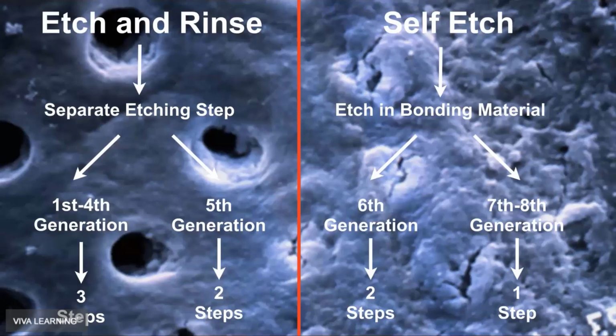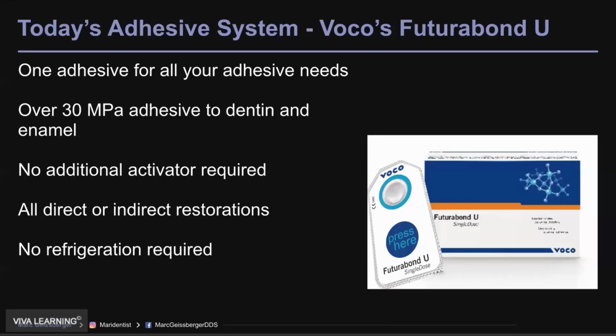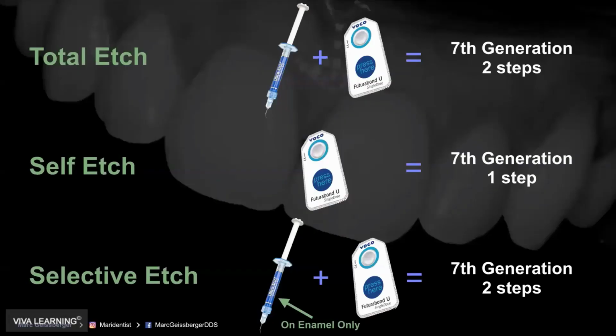Now, the nice thing about having a so-called one-step adhesive like this, a 7th or 8th generation adhesive, is it's actually more versatile than you'd think. And what I mean by that is you can take, say, Voco's Futurabond and use this as a one-step or two-step. It gives me the versatility of being able to self-etch when I want to, meaning if I'm exclusively on dentin, doing root caries, then use it in the self-etch mode. But it also allows me to incorporate acid etching when I want that. So I can use it as a total etch, I could use it as a self-etcher alone, and I could use it as a selective etching medium.